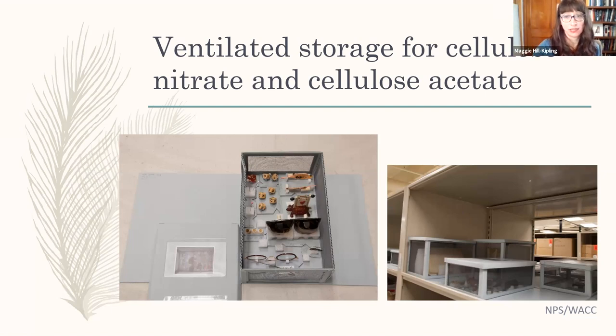These are stored high up in storage and in an area where there is a little more air exchange than other areas. You are less likely to want to use absorbents with these kinds of things because the absorbents can become quickly depleted and potentially even dangerous. You may be aware that cellulose nitrate, particularly in films like negatives, can actually become somewhat combustible. That doesn't tend to be as much of a problem with plastic materials that have been made. We haven't really seen much in the way of spontaneous combustion of those, as with negatives and historic films.